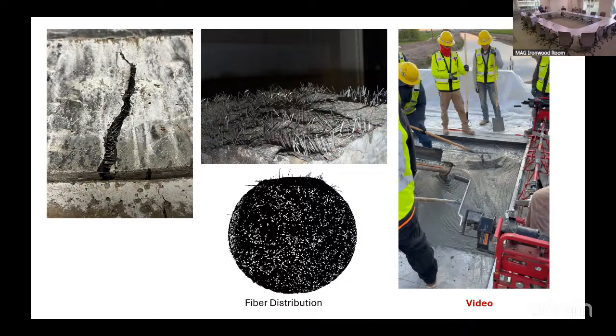There is tons of work that we've done in terms of actually addressing this from quality control. Many times you have a specification that says your standard deviation should not be exceeding this level. Well, the standard deviation of a single test is not that important, because it is the collection of, you saw all those radial cracks that we have in these slabs. It doesn't matter which crack occurs first. Normally, it is the weakest section that is going to crack. But that crack is not going to be allowed to deform until every other crack forms. So you get this complete plastic behavior where, from a plasticity theory, you get the whole deformation happening. So it is not just the weakest point that controls the performance.